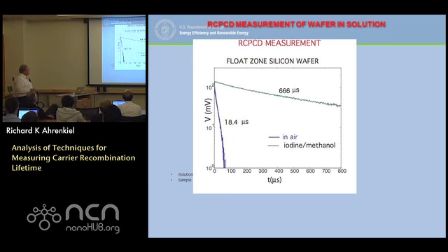So in practice, here's a float zone silicon wafer. It's not passivated, in air, put it on the platform. We measure 18 microseconds. Now, the group at MIT some years ago discovered this magic: if you take a silicon wafer and drop it in an iodine methanol solution, it passivates the surface states. These are the dangling bond states due to the termination of the surface, which is the bugaboo of all electronics. So we drop it in iodine methanol after cleaning it a bit, and you see the real lifetime is 666 microseconds because the surface has gone away.